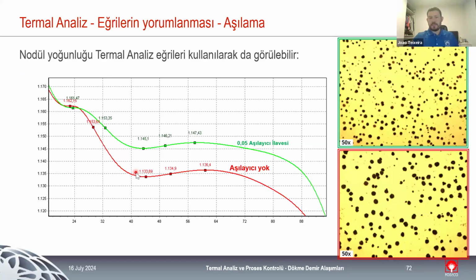And with the thermal analysis, we can also discuss the nodule density as well, because we have control of the magnesium treatment that we are going to do. And we can see here that with a small amount of inoculant, we can also improve significantly the amount of graphite nodules, because we are going to have more points for the graphite nodules to germinate. So we are improving the nodule density. And in this particular point, lanthanum, cerium, for example, bismuth, they are really important because they are really, really strong nodule density promoters. And normally by increasing nodule density, you increase mechanical properties. These are good examples of inoculants that we should use.